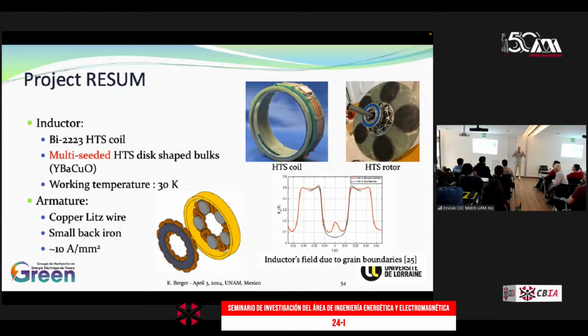In that size, we can produce a 2 Tesla background magnetic field. There is no need for iron, just using high currents with a good superconductor at a certain temperature, so we can produce this field. And the dark pellets you see here are what we call bulk superconductor. It's a superconductor, pure ceramic. With this material, when they are cooled down without magnetic field, due to Lenz's law, if you apply a variation of magnetic field across this, they will expel the magnetic field.